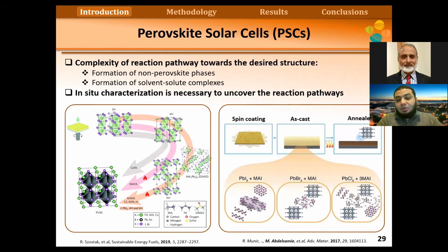But one of the challenges is that this material is more complex in terms of the synthesis. With organic materials, we synthesize the small molecules or polymers, and then we try to process the film, but we are not changing this during the processing. But for this material, we start from solution. We have isolated ions of different materials that we choose, and we end up with a final product. But on the way, we have a competition of different phases. We can form other phases, which are non-perovskite phases, and these phases are not good for solar cells. And also we can have complexes with the solvent. So the perovskite material itself can crystallize in a different structure that is not favorable, or we can form complexes with the solvents that we are using, and this makes it more complex.